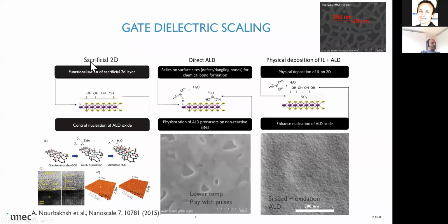Well, you can add a sacrificial 2D layer that you will functionalize. You will change the properties of that layer, and then you will use that as a seed layer. We have demonstrated that for graphene by oxidizing it and then growing a layer like that. So we could easily close the layer in 4 nanometer, and this was a record at that moment in time.